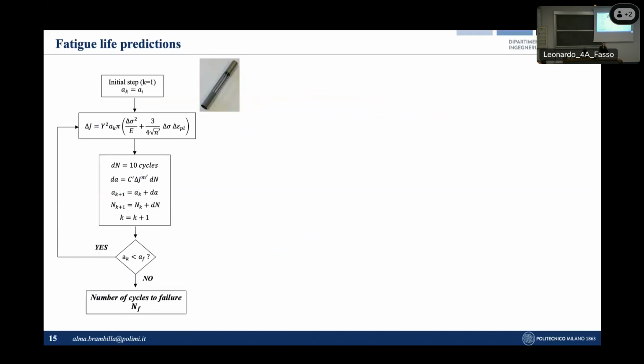So moving back to our test on multi-wire samples, at this point we had all the necessary information to calibrate a crack propagation algorithm based on the integration of the crack propagation law between an initial and final defect, updating at each step the cyclic J integral, the crack size, and the number of cycles to obtain in output the number of cycles to failure in specific loading conditions.